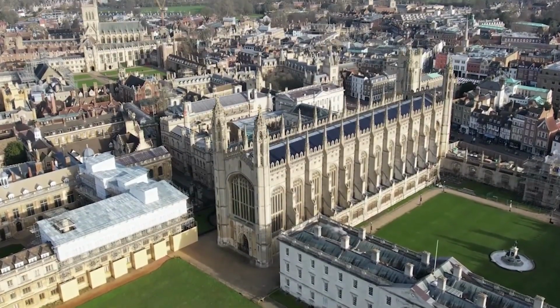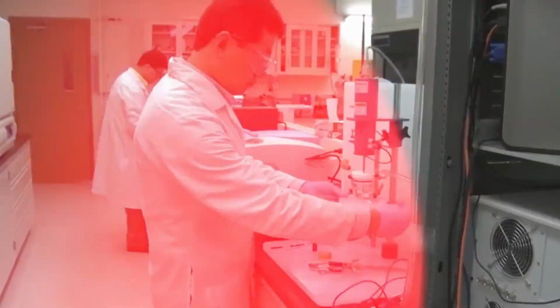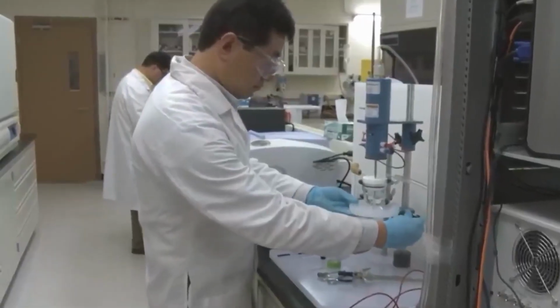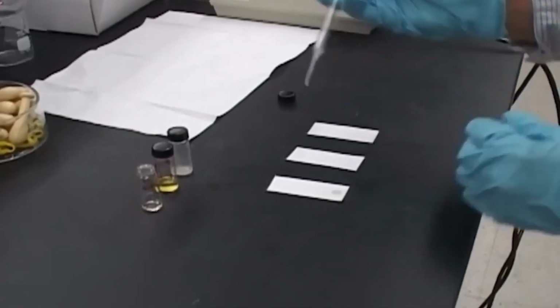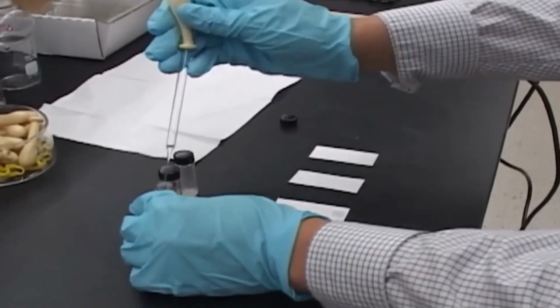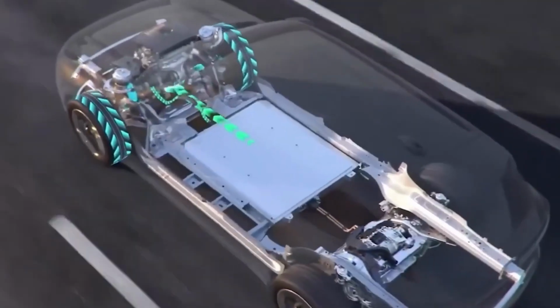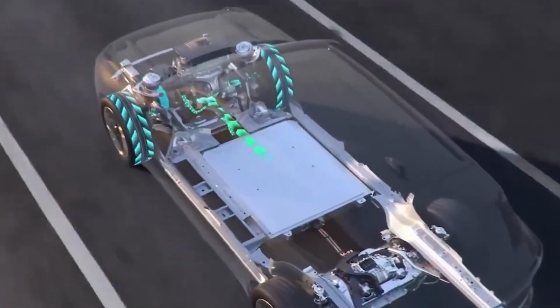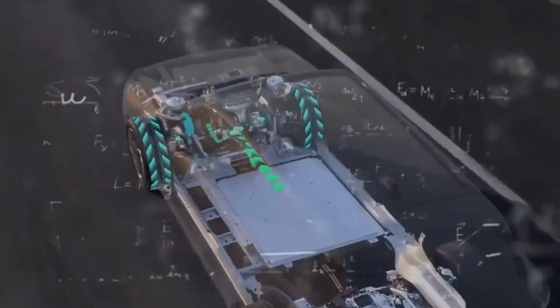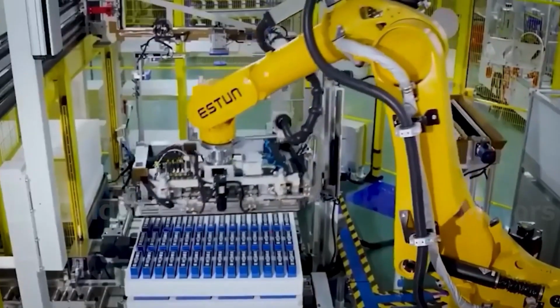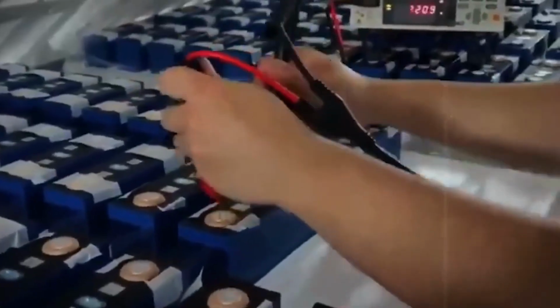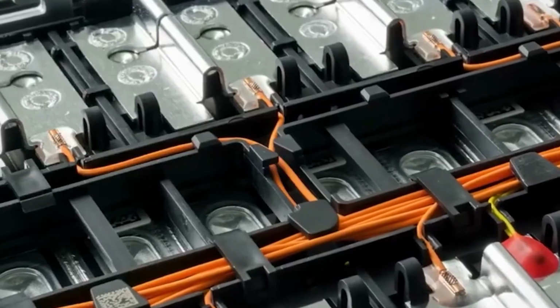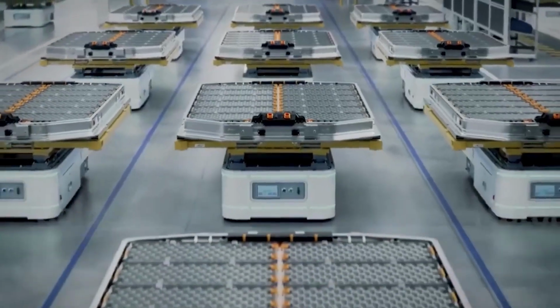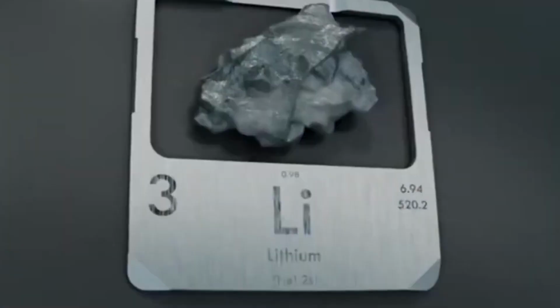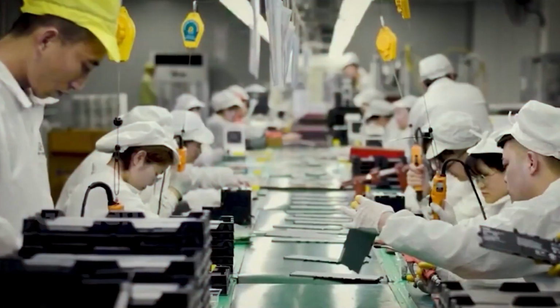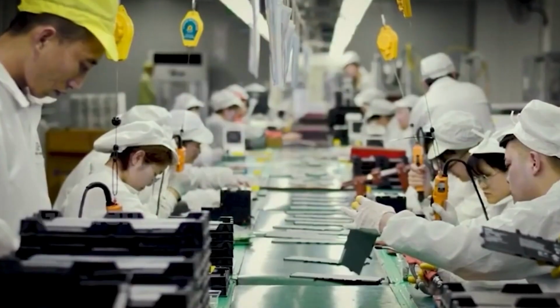For the first time, a battery material could be charged in minutes instead of hours, without shrinking the particles down to fragile, unstable nanoscale grains. Engineers had spent decades fighting the same physical wall. Lithium ions moved through a crystal lattice the way people move through a single revolving door. Add more people, and the door does not spin faster. It jams. The conventional fix was to grind the particles down to nano size, opening more doors at once, but that came at a cost. Smaller particles meant less density, higher production expense, and batteries that degraded faster under real-world stress.